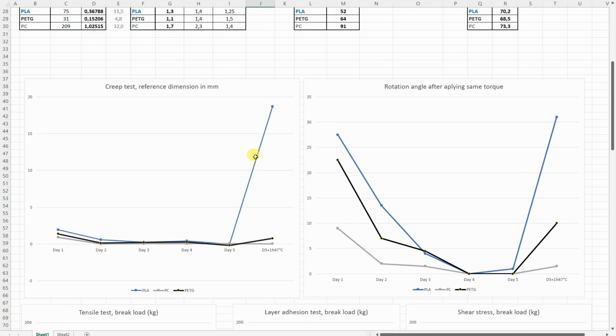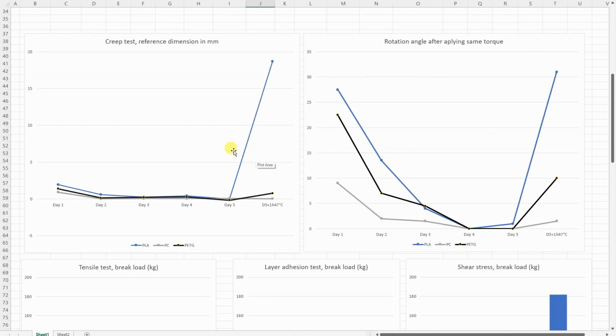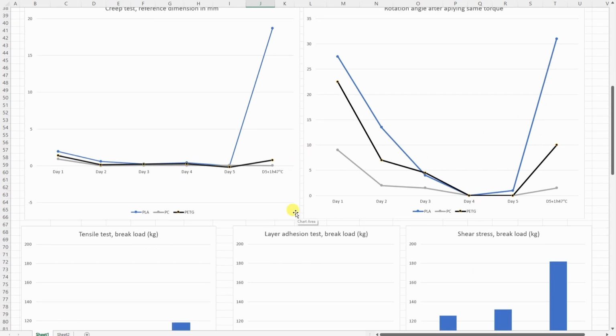But let's analyze this on graphs. So this is the creeping, this is the bending test, and this is the shear test. And as we can see, it starts with the creep, after maybe the third day the creeping stopped, and after the enclosure, well, actually we can see that the PLA deformed a lot. And very similar results we have on the shear test, creeping.